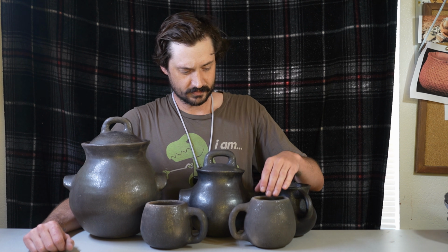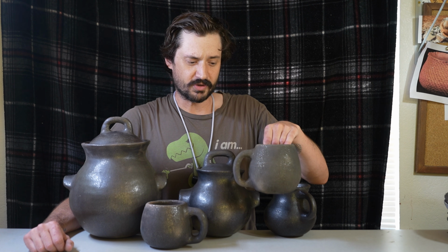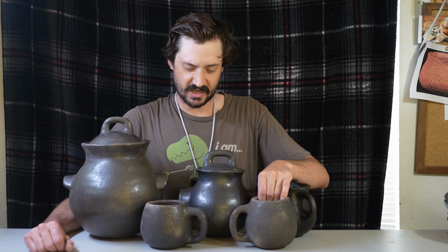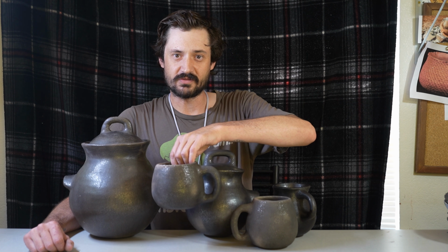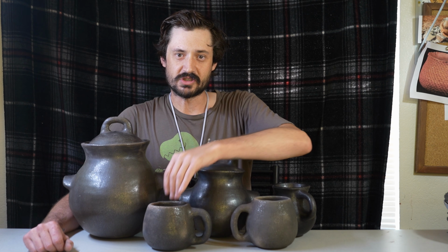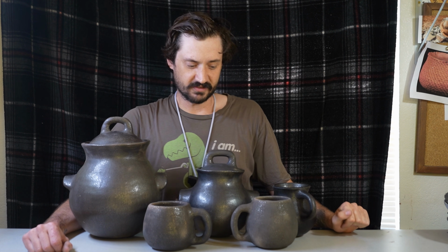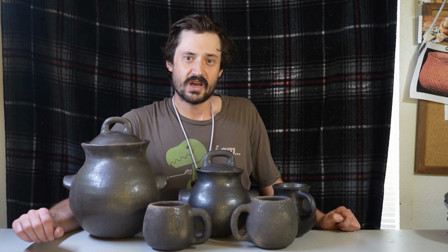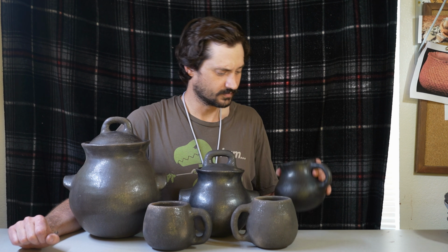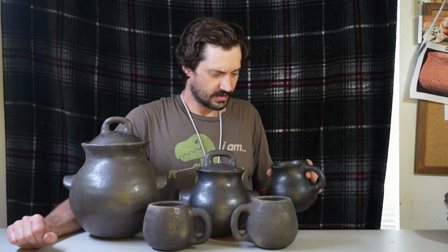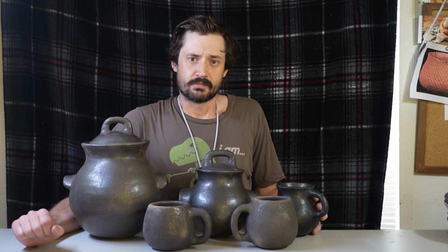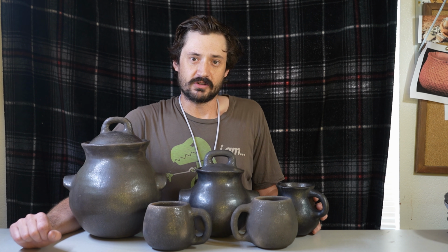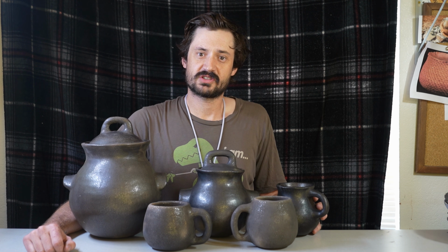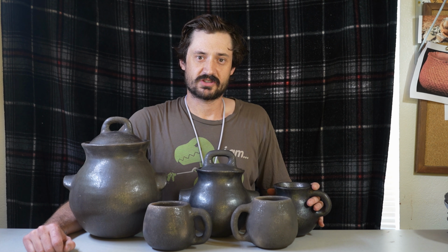Let's go over the results. The unburnished mug gained 13.5% of its weight during the water submersion test, while the burnished mug gained 12.7% of its weight during the water submersion test. That's a negligible 5 grams of difference. Although burnishing compacts the clay surface and slows down off-gassing, it does not significantly alter the porosity of the underlying clay matrix. From a human perspective, burnishing is a lot of time and energy with little functional improvement. Keep in mind this is just a pilot project, and we've only begun to scratch the surface.